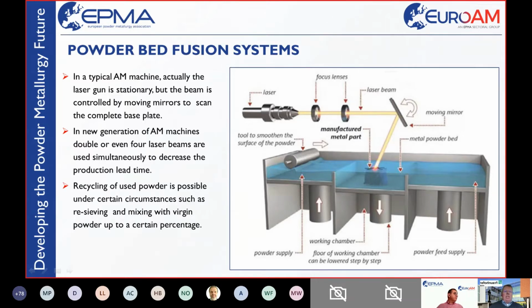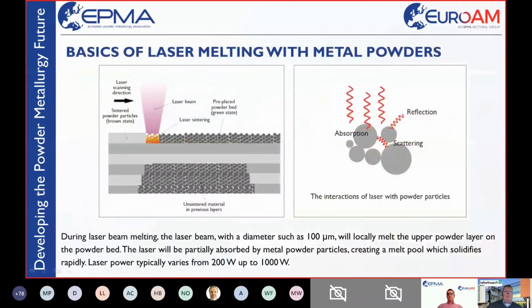Recycling, a very important aspect, is possible. Recycling of the used powder, not the one built into the product, but the powder still surrounding the completed product in the end. This powder can be sieved and re-sieved, and in some cases mixed with virgin powder, and thus reused for the next build job, at least to a certain percentage.